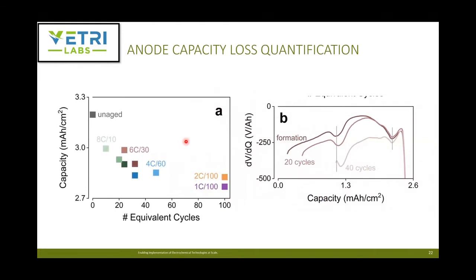And they also quantified it with the full equivalent cycles, and they attributed this loss to higher charge rates; the capacity started coming down. And not only that, even at low charge rates with lots of cycles, there was some impact on the anode capacity. So they also did a plot called dV over dQ.